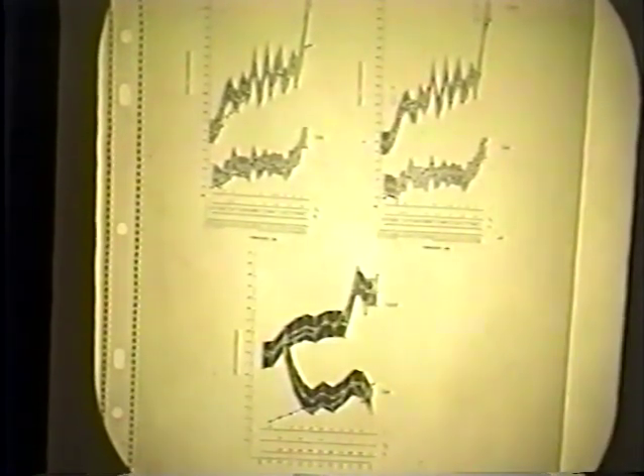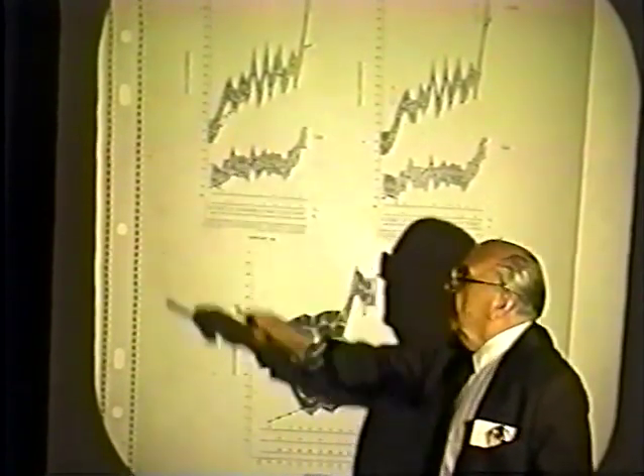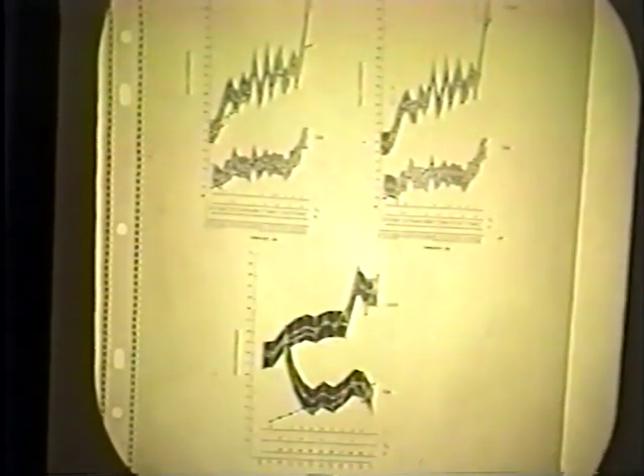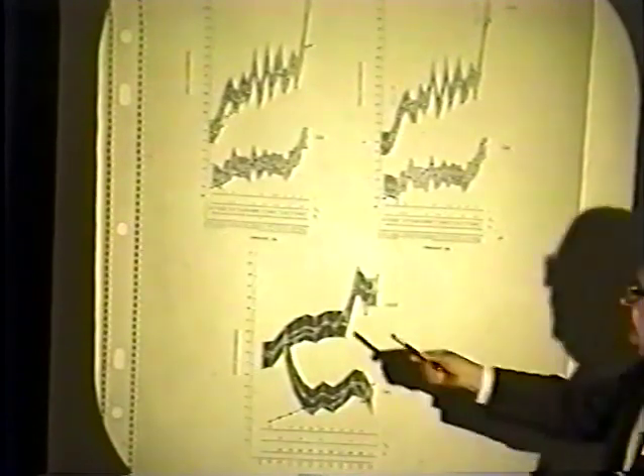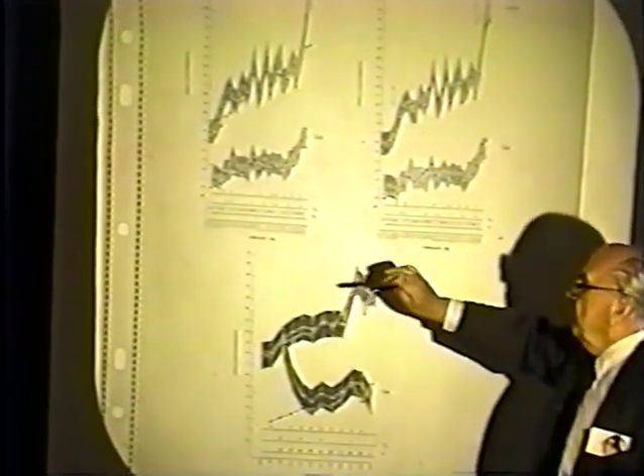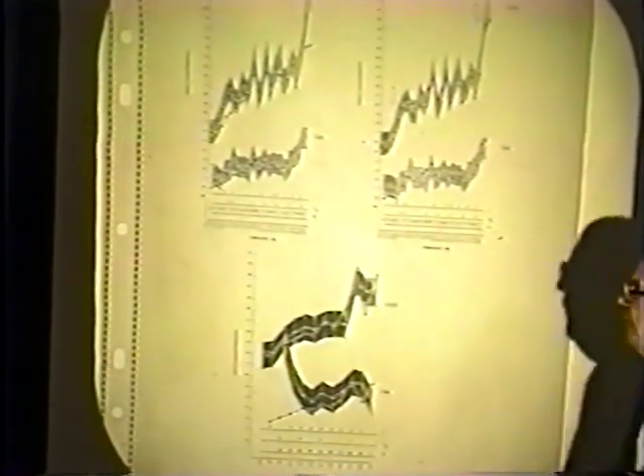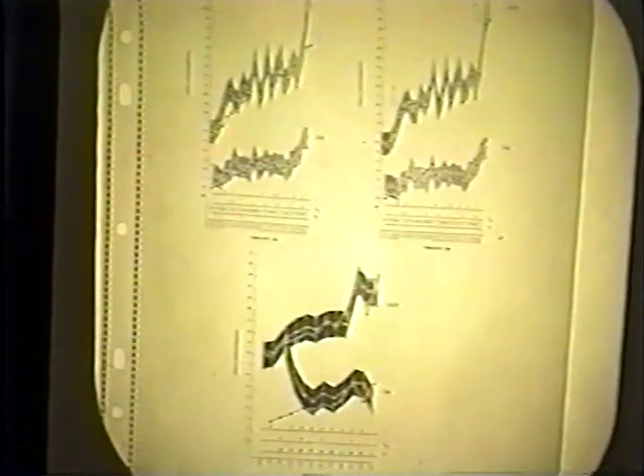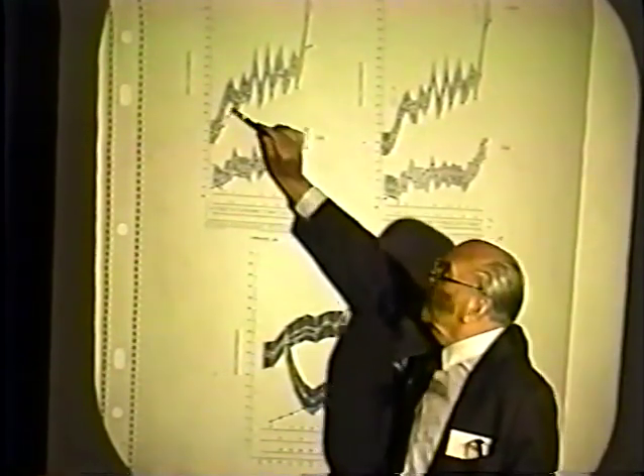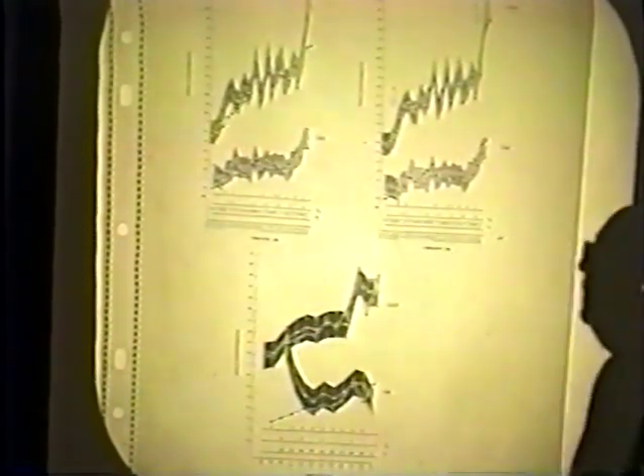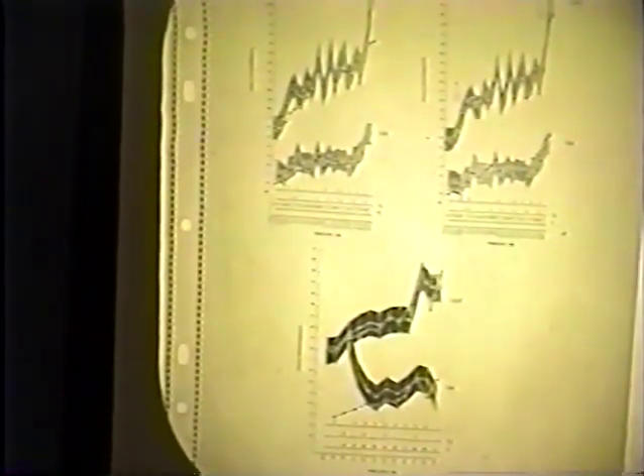So we measure each point here after a certain period of time, normally 24 hours. The dates are given here. Now, we also measure each time the current efficiency by comparing volume in the recombiner. We see here a deviation, an increased deviation, and then we see no activities at all for about 2 weeks, and then we see again activity in here.